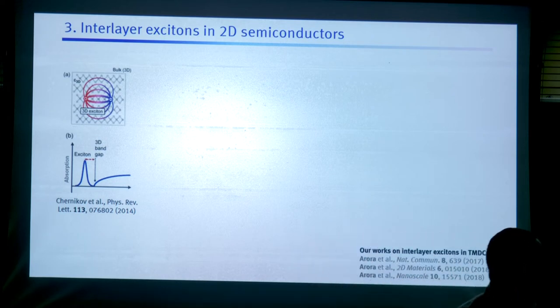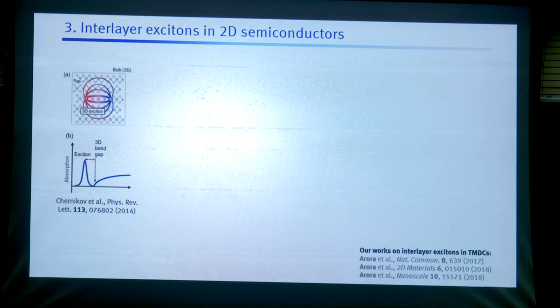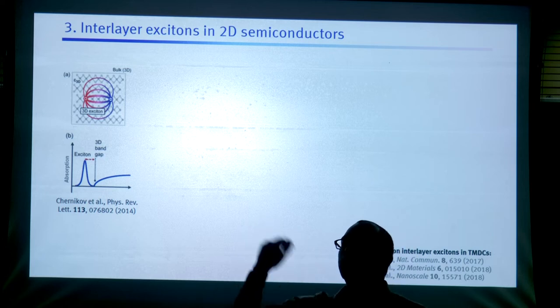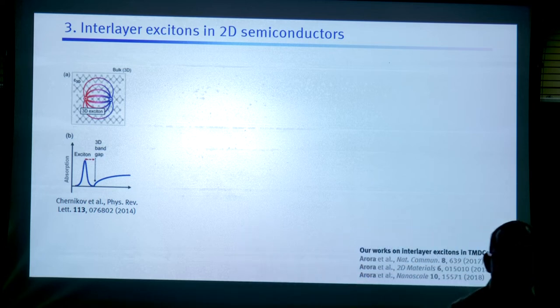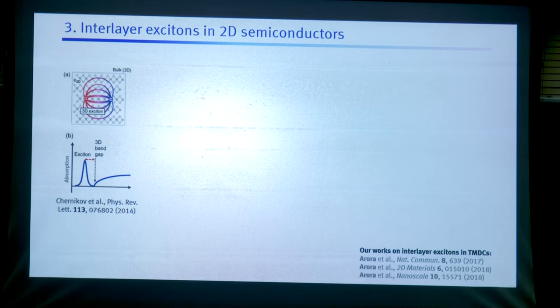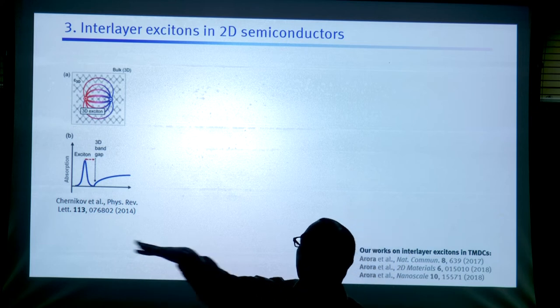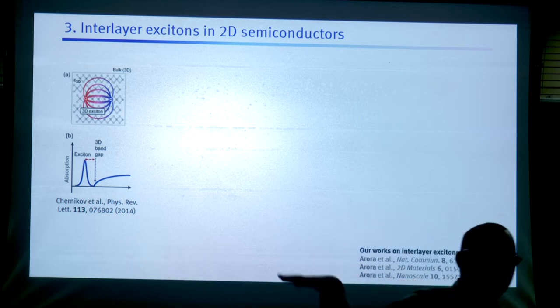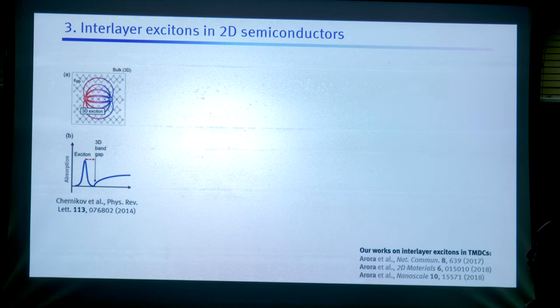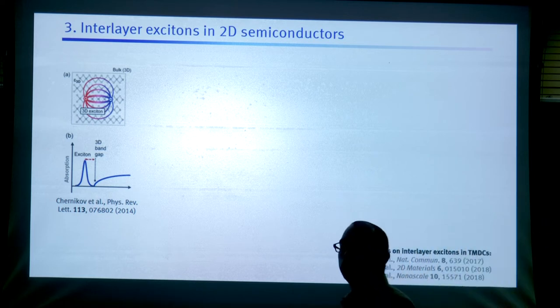I immediately started thinking that if the interlayer interaction between these layers is so weak that we are able to just peel them off, it's possible that the electrons and holes are also not talking much to each other. So that would mean that if you put an electron-hole pair, this should not be very delocalized in this direction. This should actually be mostly localized within this XY plane. So this should not be 3D, but more 2D. So even the bulk should be 2D.